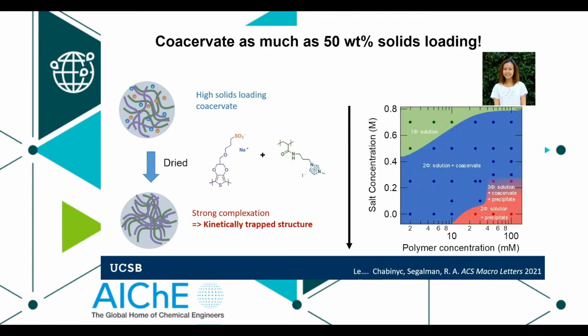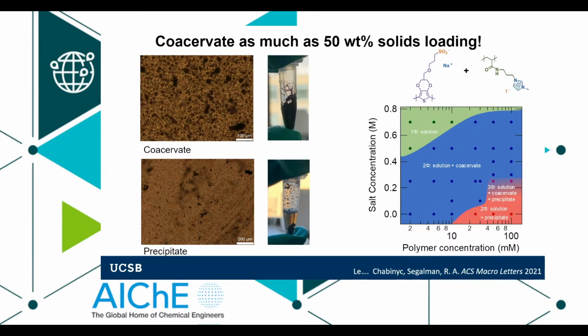Okay. It turns out that this system works really well in terms of coacervation. We actually get a huge phase window for coacervation, as you're seeing in this phase diagram, across a wide range of salt concentration, or polymer concentrations. If we don't add enough salt, the polymer will precipitate, right? It screens the interactions too much. And you can easily see the difference between a coacervate, which notably has really low viscosity because of the way the chains interact with each other, and high solids loading, and the precipitate, which ends up being a chunk, just like you would expect. Okay? And we can see the difference between these visually. Also, conjugated polymers tend to be deeply colored, and so we can easily see where we have the coacervate versus the supernatant, which appears almost clear.